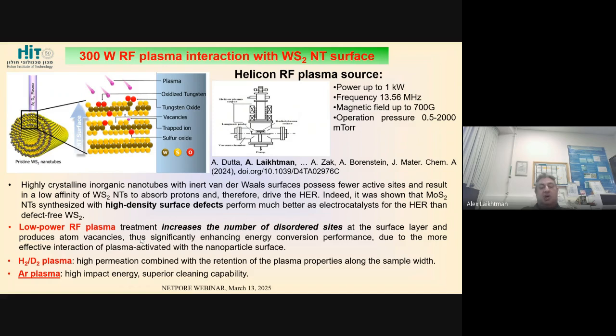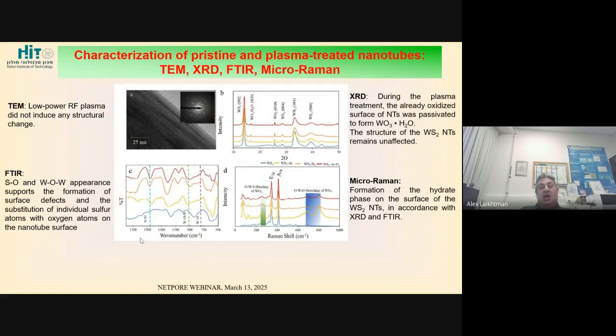So by argon plasma, we also clean all the impurities from the atmosphere and so on. So these were our predictions, and then I'm going to results. First of all, TEM shows that following plasma, there is no change in the structure. We still have quite perfect nanotube. There's an electron diffraction pattern, so this is okay.